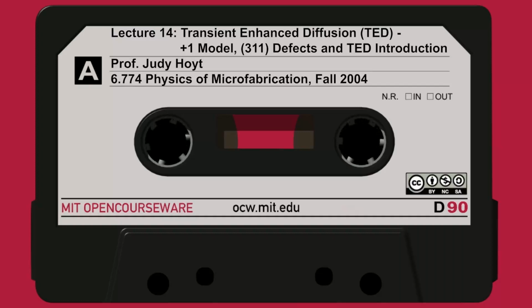These 311 defects form during the first few fractions of a second of annealing. They can even be formed during the implant itself. So their formation is important. More important is how they dissolve. They anneal out in a time range on the order of seconds to minutes, could even be longer times at moderate temperatures. Once they form very quickly, they gradually anneal out. As they anneal out, they give off excess interstitials. And it's these excess interstitials given off by the evaporating 311s that cause the boron TED that people observe.